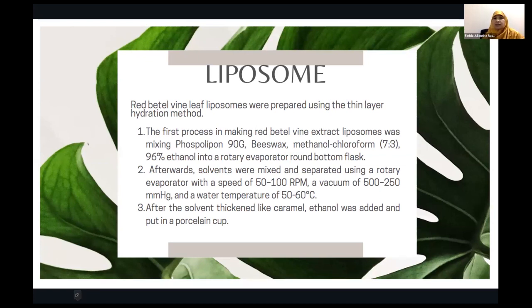The first process in making red betel vine extract liposome was mixing Phospolipon 90G, beeswax, chloroform and ethanol 7:3, 96% ethanol into a rotary evaporator round bottom flask. The second, afterward, solvent were mixed and separated using a rotary evaporator with a speed of 50 until 100 rpm, a vacuum of 500 until 250 millimeter of mercury, and water temperature of 50 until 60 degrees Celsius.